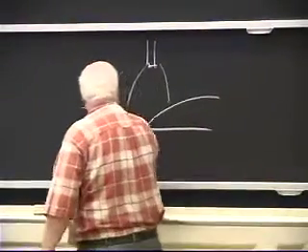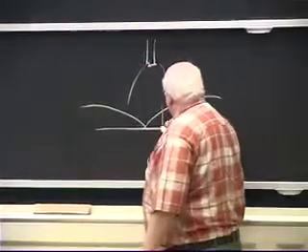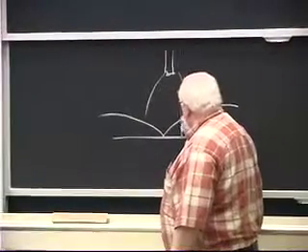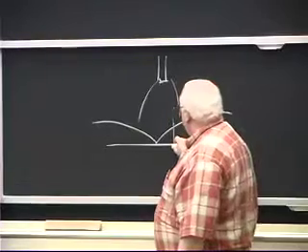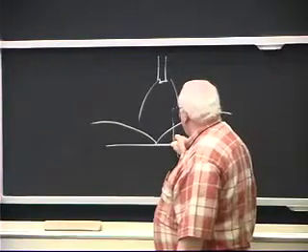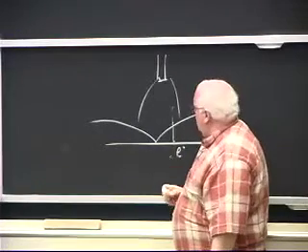Anyway, we've said that 80 to 90% of the heat is carried by the electrons going across this gas boundary layer. So if this is my arc and this is my surface, I've got a gas boundary layer, and the electrons punch through and carry with them the heat, the Thomson energy, the energy achieved by being accelerated across the anode fall space, and then decaying down to Fermi energy.